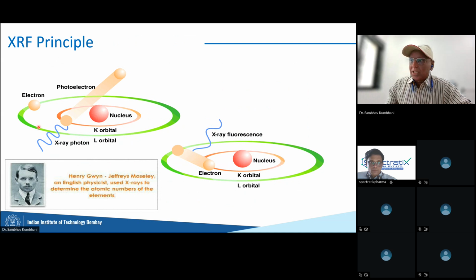Working principle, very simple. You hit an atom with a very high energy X-ray. This X-ray has enough energy to knock out one of the innermost electrons of the atom, typically from the K orbit. When an electron is removed, a hole is created in that space. Of course, the atom does not like a hole. So one of the electrons from the outer shell jumps back into the K shell to fill the hole. And obviously there is an excess energy between the outer and inner layers. That excess energy is released as fluorescence. We measure the energy of this light and identify what element it is, because each element has a very specific distance between its K, L, M orbits. The energy associated with each orbit is very specific, so we can very confidently tell what element is present based on the energy of the fluorescence we measured.